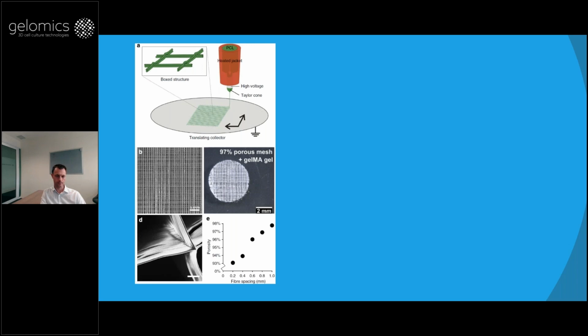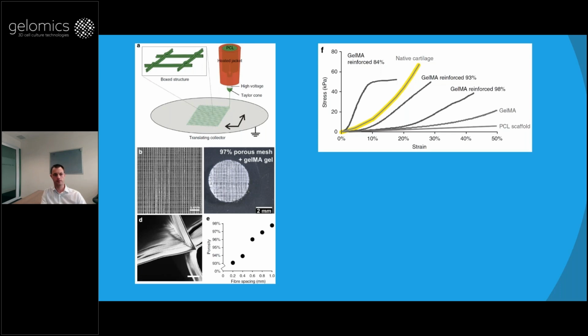porosities. With this, we made these scaffolds and infused them with GelMA, cured the GelMA, and then we could get quite close to the mechanical properties of native cartilage. So you can see the bottom two curves are just plain GelMA, or the plain scaffold, but the combination of them works synergistically and makes this reinforced GelMA that is both a lot stiffer, so it approaches the stiffness of cartilage, but it's also compliant, so you can compress it much more than you can